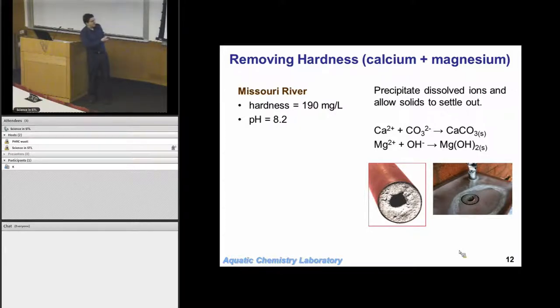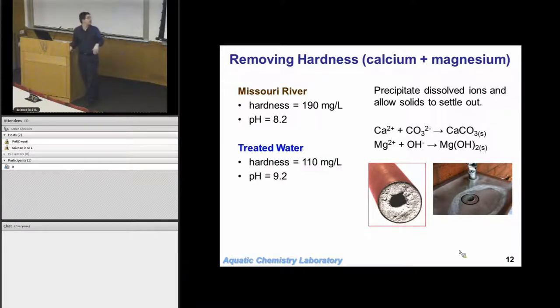Well, in order to precipitate out the calcium as calcium carbonate and the magnesium as magnesium hydroxide, we had to increase the pH because we wanted a hydroxide, and we have more hydroxide at high pH. So at the water treatment plant, the pH might come up to 10 or 11, and they don't even worry about bringing it all the way back to 8.2. So our treated water has a hardness of about 110 milligrams per liter, and a pH of about 9.2. So 9 to 9.5. If you take St. Louis tap water, go home, take some pH paper. If you want, run up to the lab. I'll give you a piece before you leave. Or if you have your own pH electrode, you can measure, and it's about 9.2. And most people think it's like 7 or less than 7. 9.2. And it's because of the chemistry to remove the magnesium and the calcium.